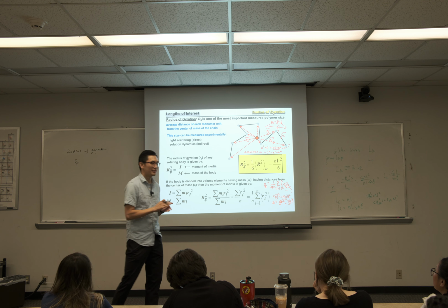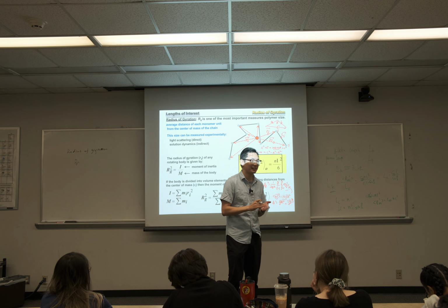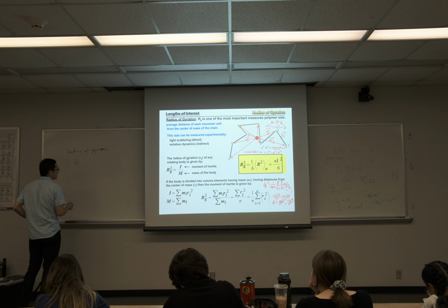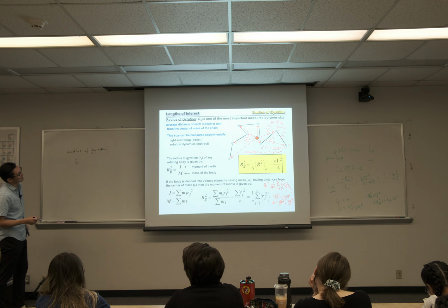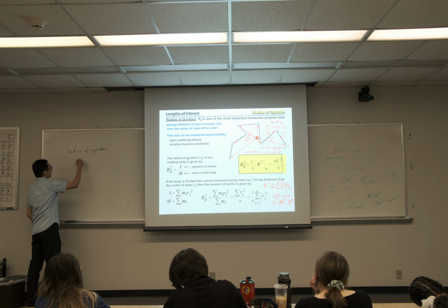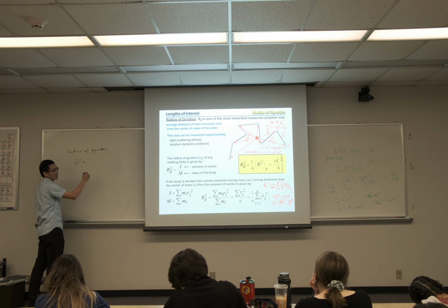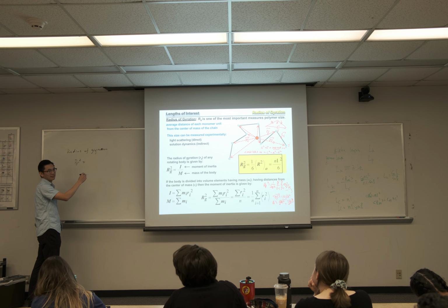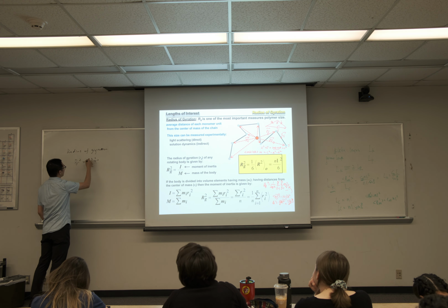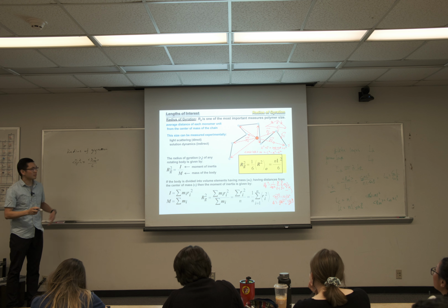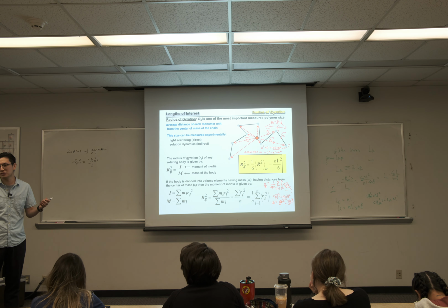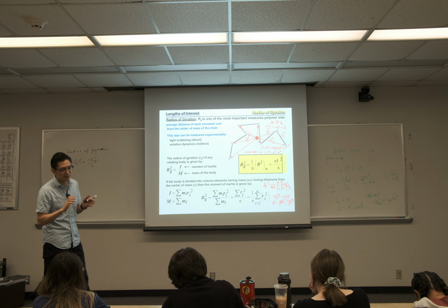It's like you go to a wellness check: that's your height, your weight. These things are measurable. For a polymer, we can measure it by Rg. And radius of gyration is a parameter we can measure. I'll tell you directly, Rg squared is related to end-to-end distance: Rg squared equals one sixth of R_EE squared, average. So our end-to-end distance squared is 6 times bigger than Rg squared. If we measure Rg squared, you will be able to get the end-to-end distance.